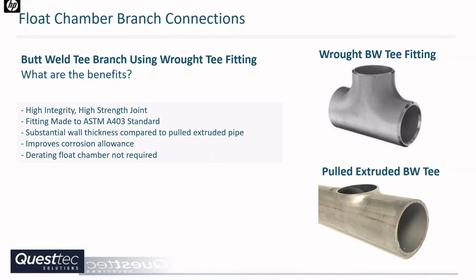And what are the benefits of that? It does yield a high integrity, very high strength joint. The fitting itself is made to ASTM A403, and that wrought butt weld fitting offers a substantial wall thickness compared to a pulled extruded pipe. When you pull extruded pipe, you're also thinning the wall of that pipe. So the wrought T fitting will improve corrosion allowance, and it will also not require any derating of the float chamber since you're not thinning the wall.